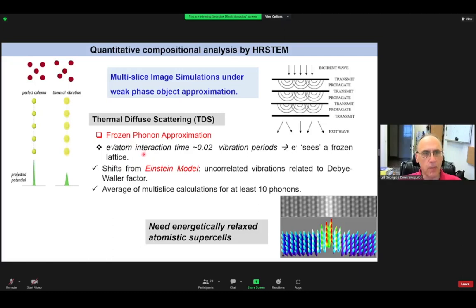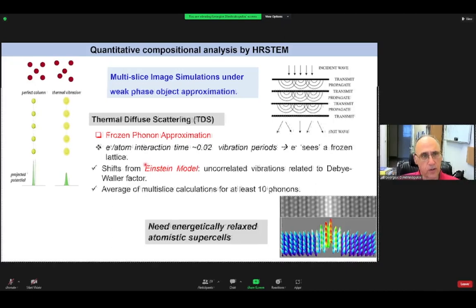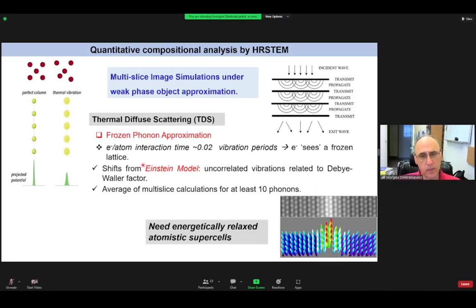In other words, we make different, let us say, photos of the material in different phonon states, different vibrational states. We use the Einstein model of uncorrelated vibrations. And then if you calculate, let us say, 10 phonons or more, then you are quite accurate and you can do the overlap of these 10 phonon calculations and get your simulated model.